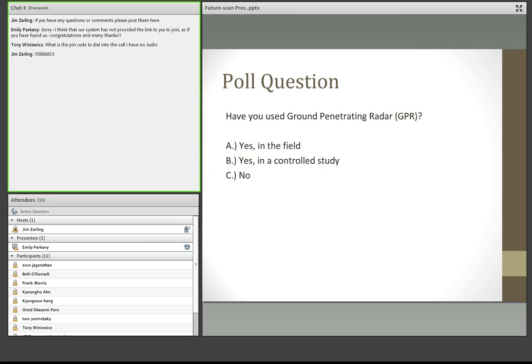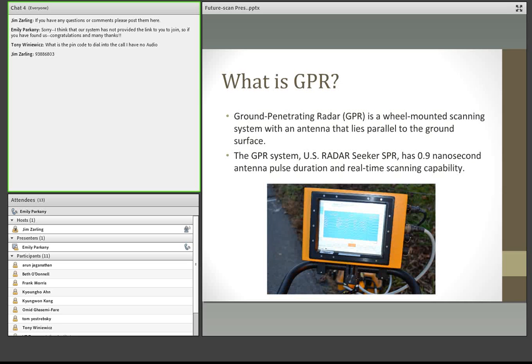For those of you that have not used it, GPR is a lot like FutureScan, simply in the fact that it's sort of a separate radar scanning system. The difference is that GPR uses different wavelengths and antenna pulse width durations, and also it's only used from the surface, the ground surface. The specific GPR system that we used in this study was a US RADAR Seeker SPR, and it also had real-time scanning capability. And you can see in the picture there one of the radargrams from one of the tests that we did during this study.